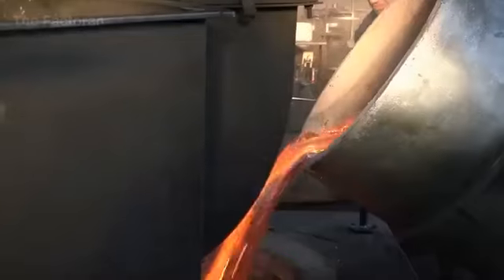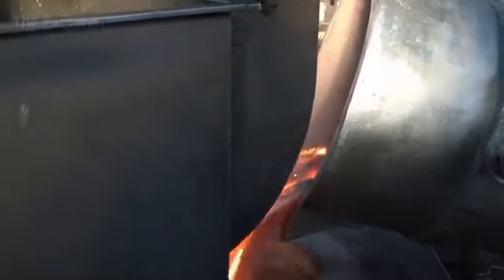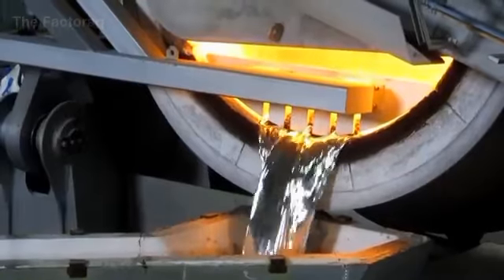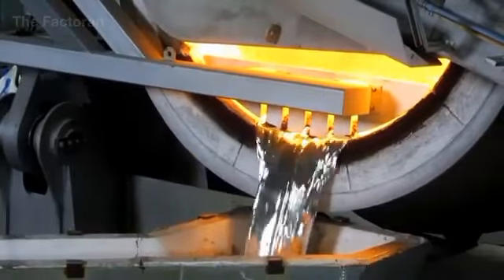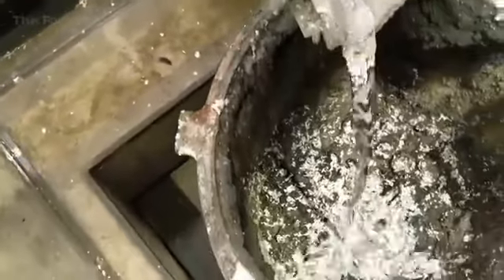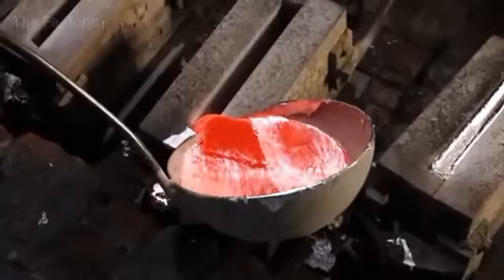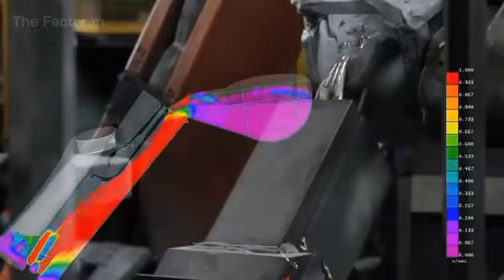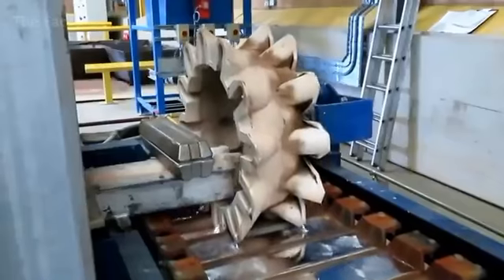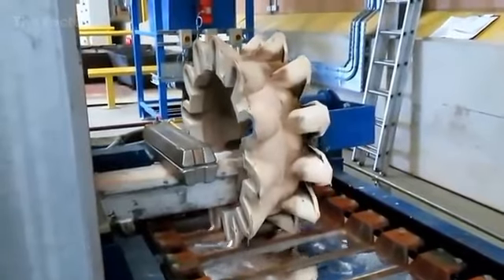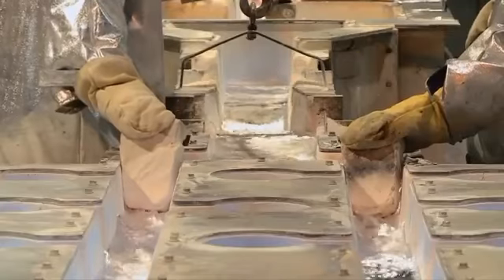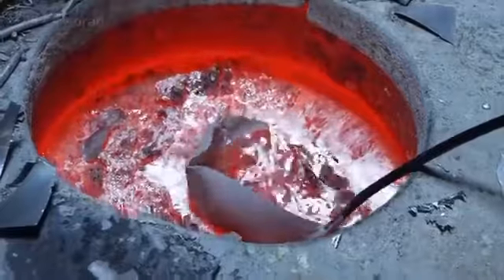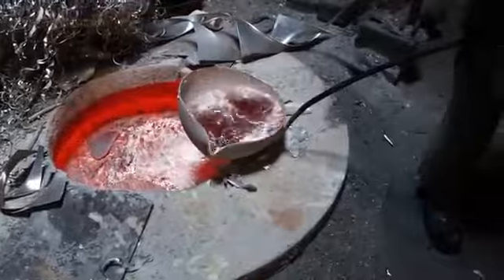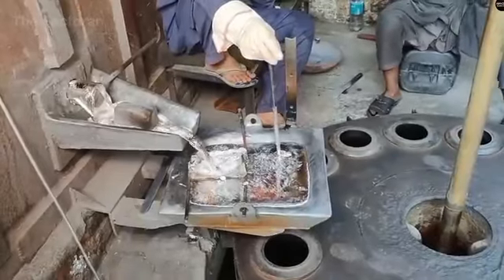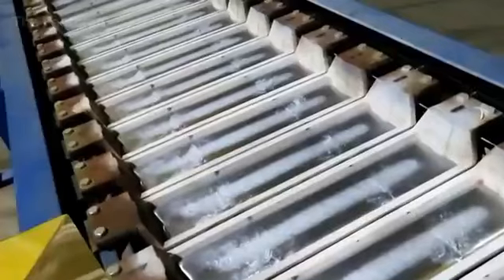If poured too quickly, the aluminum can form gas pockets or surface cracks. If the mold is too cold, the metal may solidify unevenly, leading to internal structural flaws. Each parameter must be carefully balanced, much like keeping a steady stream flowing through a narrow gap. A slight deviation can distort the entire shape of the final product. In many modern facilities, the casting process is fully automated. Sensors continuously monitor pouring height, cooling rate, and surface temperature. Yet in some semi-manual lines, skilled workers still control the flow, a task requiring sharp instincts and split-second precision.